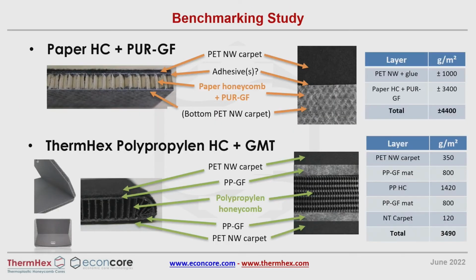And if you compare the different materials, above you have the paper honeycomb polyurethane, which was the previous solution, which is based on paper, but with the polyurethane impregnation, it's not recyclable anymore. And our thermoplastic solution is complete polypropylene glass fiber and can be ground and recycled.